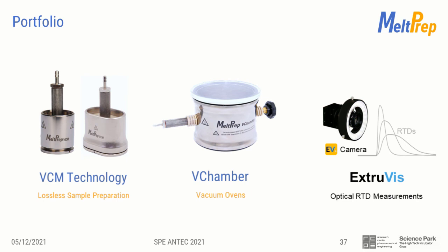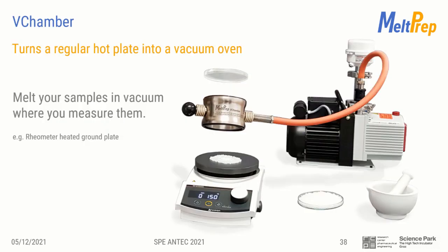You already know the VCM technology for the lossless preparation. The second innovation is called the V-chamber. The V-chamber turns a regular hot plate into a vacuum oven. Place your sample onto the hot plate and put the V-chamber over it. You can apply vacuum and melt or dry your sample directly under vacuum on your hot plate. You can even think of using it on your measurement instrument directly, on the rheometer, for example.